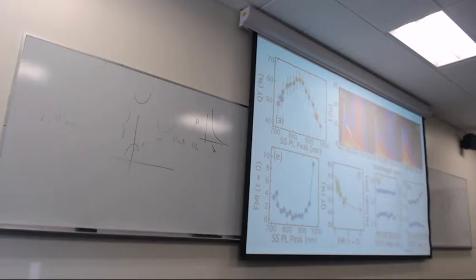It's very, very weak. Wait, what's the time range for your integration? This 45 nanoseconds, and then we go from basically 100 nanoseconds out to a millisecond. We have two different detectors. So one is probing this, which is really, really slow because it's indirect. It's got to wait around for a phonon, so it doesn't do anything, and it's also not very bright, right?